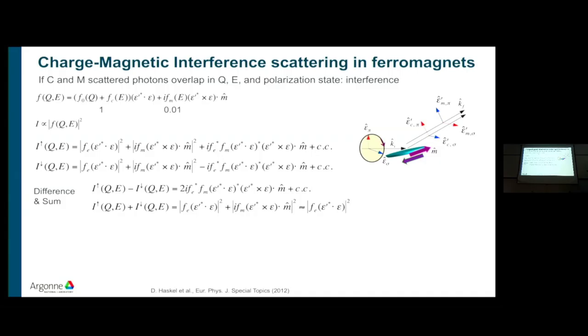And if I add these two for different directions of magnetization, then this term cancels, and I get this plus this, maybe divided by 2. And then we set the magnetic scattering. We know this term is 10 to minus 4 of this guy, so we can neglect it, and so we get the charge scattering. And then you can take the difference divided by the sum. We call that the flipping ratio, but the point is that this quantity now is large, because this was 1 and this is 0.01. Now I have a 1% quantity. The product is 1%. It's no longer 10 to minus 4. So again, 2 orders of magnitude. It's not a pure magnetic signal, but it's sensitive to the direction and magnitude of the magnetization.